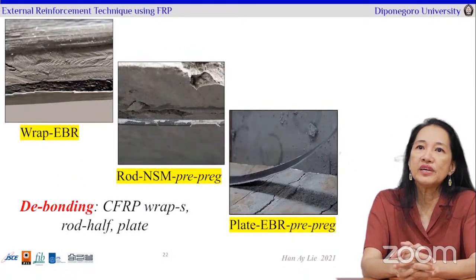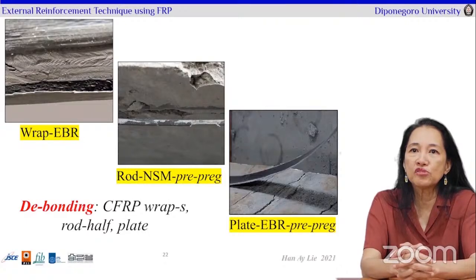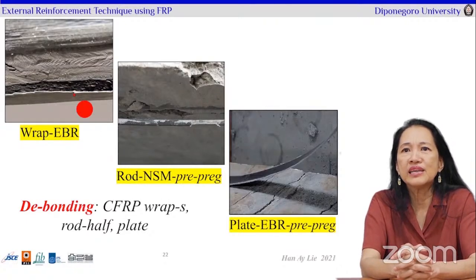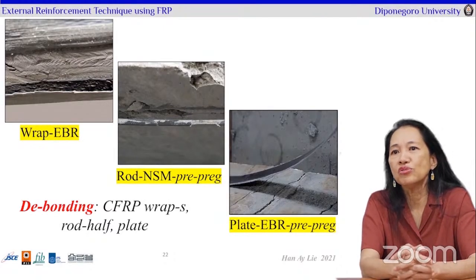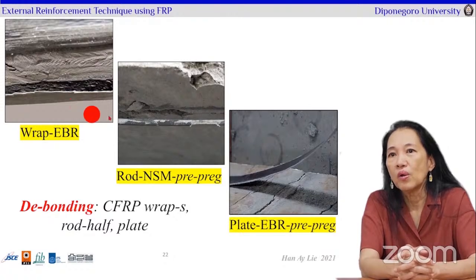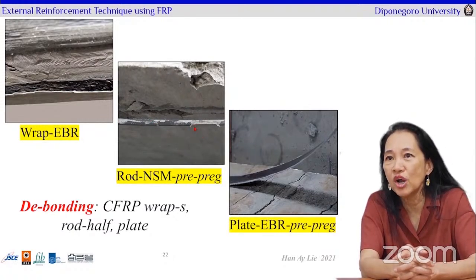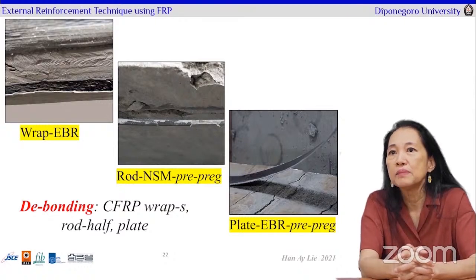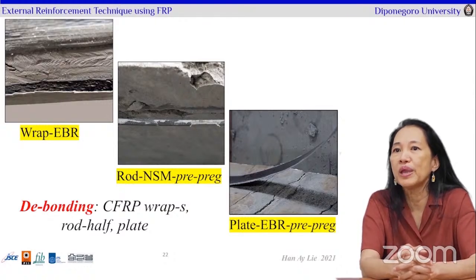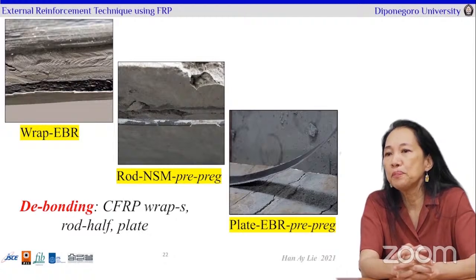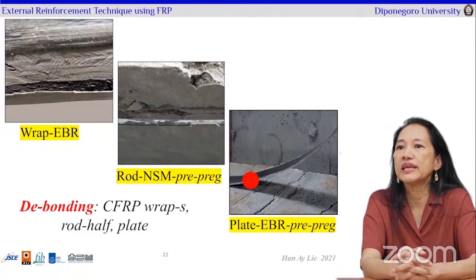Here we have the externally bonded reinforcement wrap. You can clearly see that there is the debonding between the wrap and the concrete. This also occurred for the rod, which was near surface mounted, so you can still see the hole where it was planted, but still it came out, so we have the debonding. And for the plate, we also have the debonding in the ITZ.